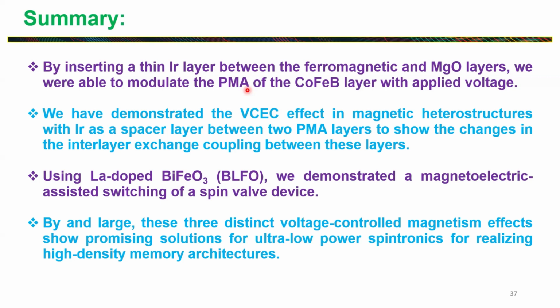two PMA layers. And then we have shown that when you dope BFO with lanthanum, you can switch the spin with just the electric field, and the corresponding energy requirement comes in attojoule per bit operation. So what I can say is that by and large, these three distinct voltage control magnetic effects are a promising solution for ultra-low power spintronics for realizing high density memory architecture.